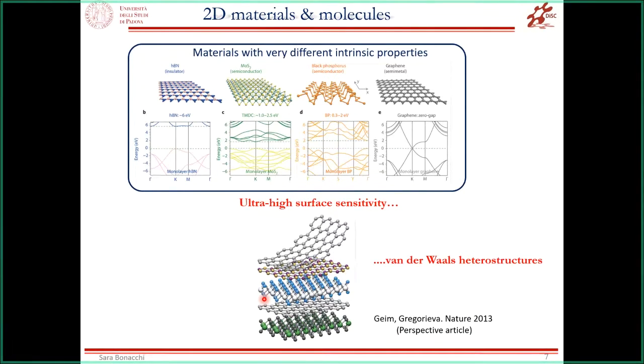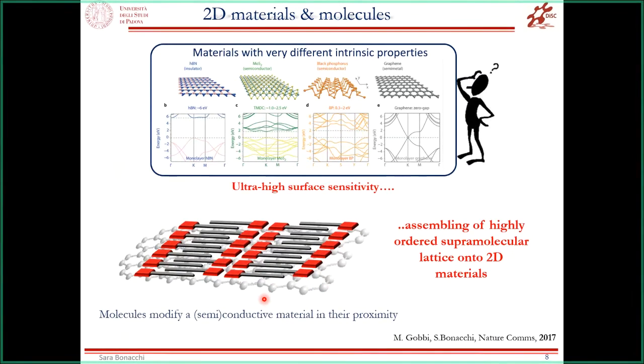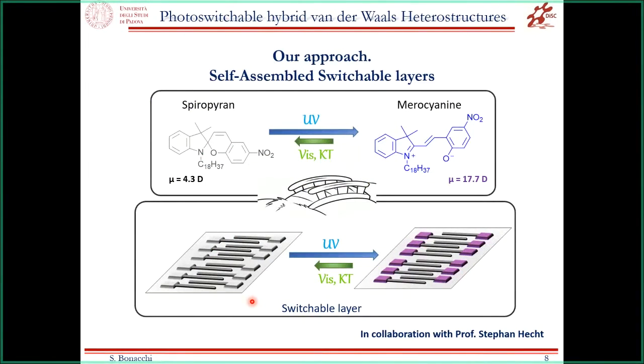optical and electronic properties. But as chemists, we were wondering how we can play with this fascinating 2D material, and in particular, how we can tune the electrical and optical properties of these two materials by playing with these two dimension and molecule at the same time. And our approach was something that I create during my postdoc at the University of Strasbourg in the group of Samori. Our approach was to use high-order assembly supramolecular molecule in order to create a sort of lattice, high-order supramolecular lattice on top of a 2D material, and use this high-order molecule to tune the conductive properties of the graphene and of the graphene layer.